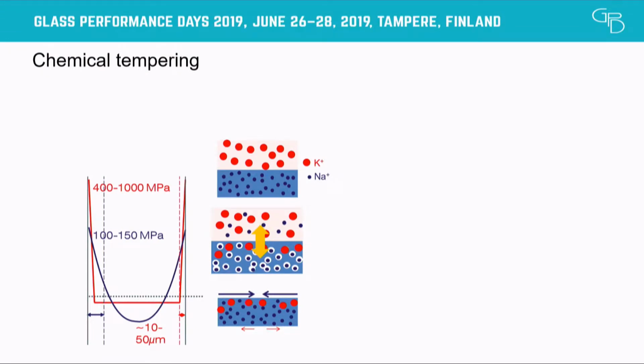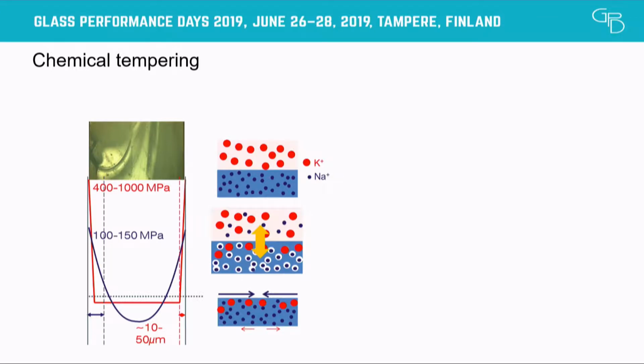The problem of this precompression is that it cannot go very deep in the glass. And what does it mean? The precompression that I show in this picture actually includes thermal tempering, which is the most common stress profile that we normally have in glass when we consider it tempered. And then there is the profile of chemically tempered glass. And as you can see, what we call the case depth or the depth of layer, which is the depth at which the precompression reaches zero, is very narrow in chemical tempering and is much deeper for thermal tempering. And so if we take, for example, an image of a glass with an artificial scratch, we see that these flaws or these cracks tend to propagate quite deep in the glass thickness. That means that the depth of layer during chemical tempering is quite important, and it's fundamental.